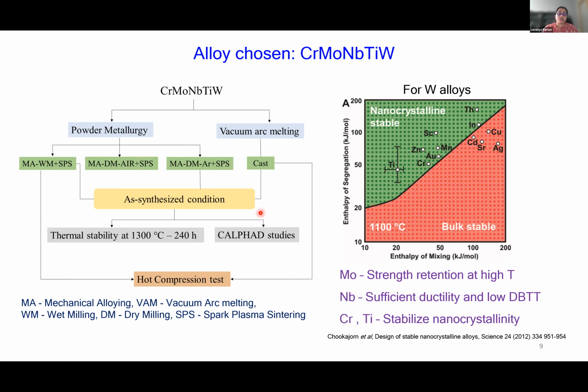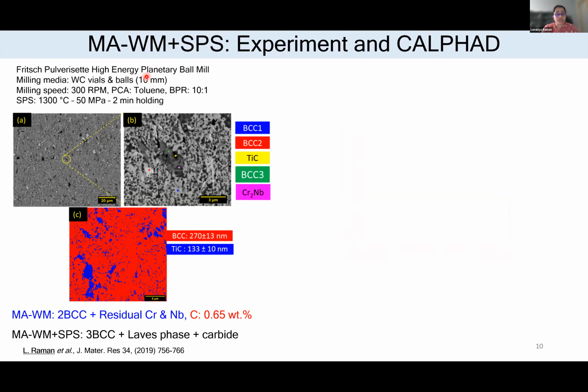We have tried to characterize the alloys in their as-synthesized condition. The experimentally observed phase formation was validated through CALPHAD studies, and we also studied the thermal stability. Finally, the deformation behavior of the cast alloy and the wet milled alloy has been studied. I'll be showing these things in detail. To start with, for the mechanically alloyed wet milled condition, we used a Fritsch high energy ball mill, where the individual elemental powders were added in equiatomic proportion.